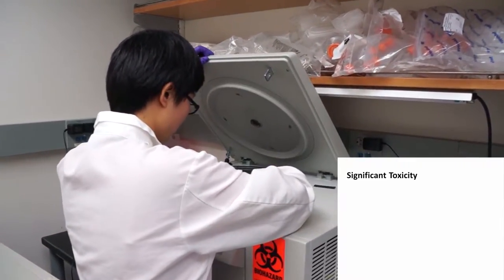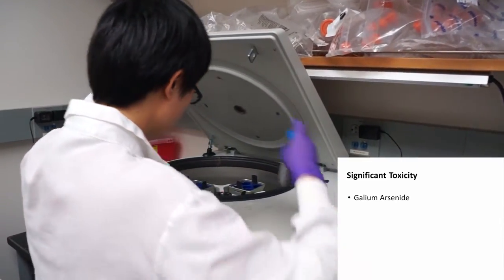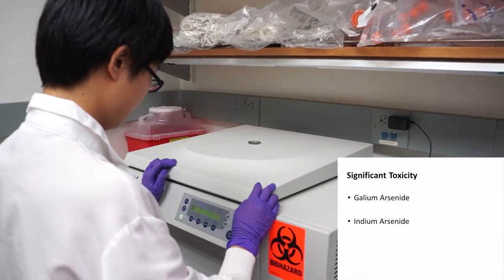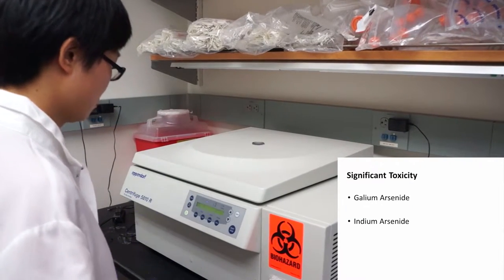We found that nanosized 3-5 arsenides, including gallium arsenide and indium arsenide, could induce more significant cell toxicity at 24 to 72 hour observation periods.